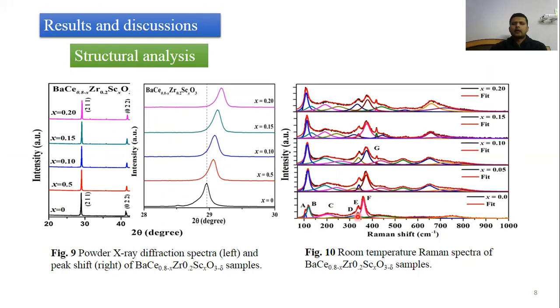The band between 300 to 400 centimeter inverse represents the perovskite phase, where the bands E and F correspond to the stretching modes of the BO6 octahedra, while the band D represents the bending of the octahedra. While the bands at the lower frequency region, that is 85 to 100, marked A and B, represent the vibrational modes for barium BO6 dodecahedra, where the motion is mainly due to the barium ions.